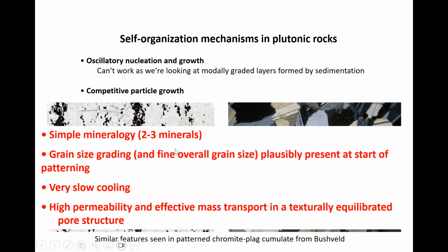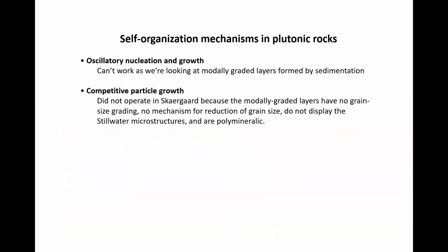Right, so simple mineralogy, grain size grading, which is inferred. We can easily do it with melt back from this open system Stillwater example. We've got very, very slow cooling rates, and we've got this high permeability and effective mass transport. That all works for Stillwater and Bushveld, but it doesn't work for Skaergaard.